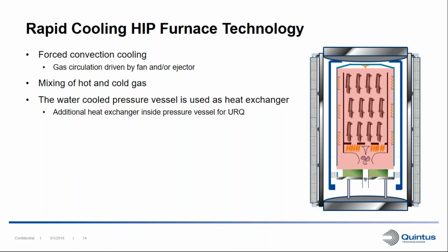As a part of the furnace surrounding the hot zone, we have an insulating thermal barrier. And this is to protect the pressure vessel from heat. So during a HIP cycle, we have high pressure gas in the whole pressure vessel, but we only have the high temperature in the hot zone. So what we do when we want to achieve the cooling is we start to circulate the gas inside the pressure vessel. And this is driven by either a fan or an ejector or a combination of both.